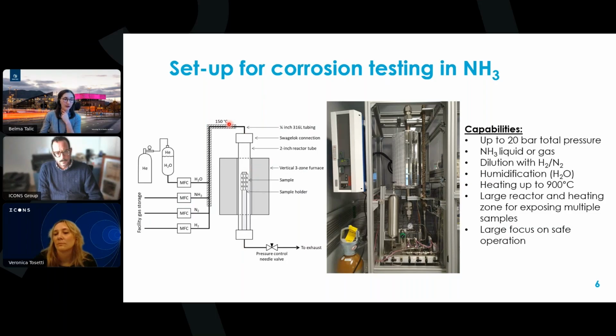For the gas tubing, the heated zone here is made of Inconel 600, and then the cold zone is made of 316 components. And also these Swagelok components are 316. So we've checked with laser thermometers and so on to ensure that the temperature of these Swagelok components is sufficiently low that we don't have significant nitridation of the components.